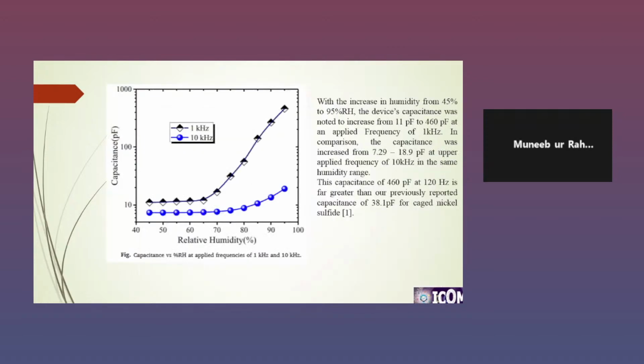These are the results of the capacitance at different frequencies. We increase the humidity from 45% RH relative humidity to 95% RH. We can see that at low frequency, at 1 kilohertz, the capacitance of the device changed from 11 picofarad to 460 picofarad. So we see that as the humidity is increased beyond 65% RH, the capacitance is abruptly increased to 460 picofarad.